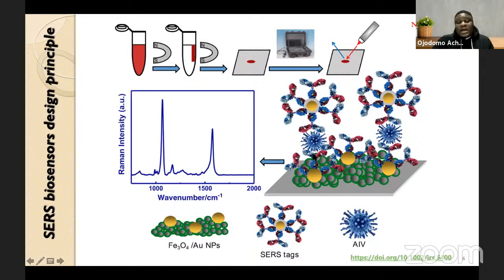So in the presence of another equally targeting antibody that can capture the virus or your target analytes, as the case may be, you can form a sandwich nanostructure between the substrate material, which is in this case magnetic gold nanoparticle labeled with the specific antibody for this virus, and the corresponding SERS nanotag, which has also been labeled with an antibody for the virus. After magnetic purification and separation of this whole immunocomplex from the sample matrix, you can drop cast it on a substrate, which could be a smooth glass, or in some cases we can also functionalize the SERS substrate, which I showed earlier on. Then you can take your direct SERS measurement and generate a signal like this.